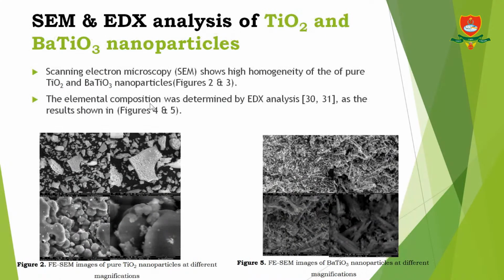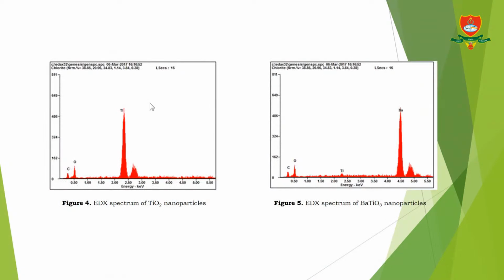Next, SEM and EDX analysis of titanium dioxide and barium titanate nanoparticles. SEM shows high homogeneity of pure titanium dioxide and barium titanate nanoparticles. The synthesized pure titanium dioxide nanoparticles are observed in irregular shape and barium titanate is observed in rod-like structure. This graph shows the elemental composition determined by EDX analysis. Conclusion: pure titanium dioxide nanoparticles are observed in irregular shape and barium titanate in rod-like structure. The EDX spectrum has prominent peaks of titanium, barium, and oxygen, confirming the formation of pure titanium dioxide and barium titanate nanoparticles. Thank you.